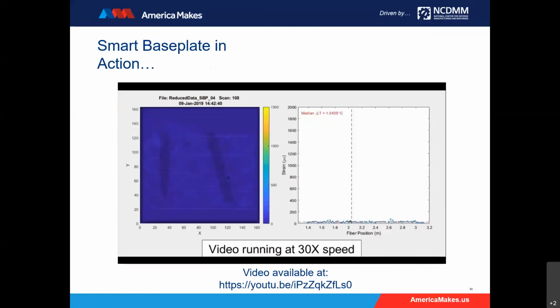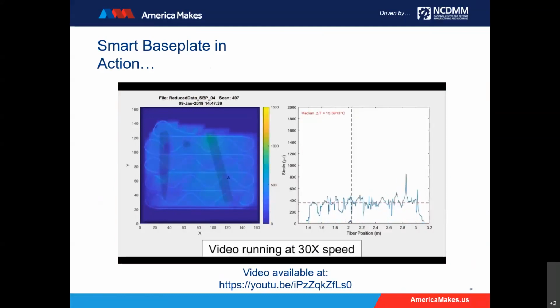And here we are actually welding, and you'll note those blue waves that follow, that's actually strain in the build plate being created by melting and resolidifying of the powder. So we're actually watching the strain evolve in the part over time. Now this is sped up 30x, if you didn't know that, note that. But you can actually see the strain as each pass of the laser goes back and forth.